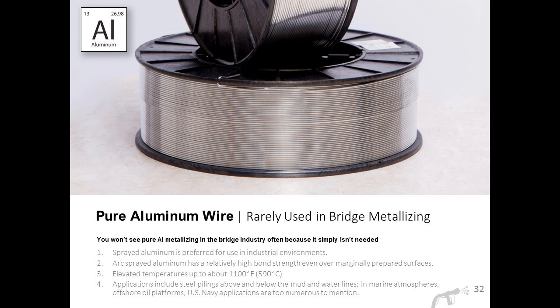Sprayed aluminum is really preferred in industrial or heavy manufacturing environments because, again, it can really extend the life of its substrate versus chemicals that would be found in an industrial sector atmosphere. As you get more chemicals in the air, that certainly affects the corrosion rate, and aluminum does a really good job of dealing with some of those chemicals. At elevated temperatures up to 1100 degrees Fahrenheit or 590 degrees centigrade, for example, on the fire side of a fossil fuel boiler tube, aluminum would be a really great choice. But for the bridge industry, we're basically just looking at outside temperature ranges that we hope would never reach 1100 degrees.